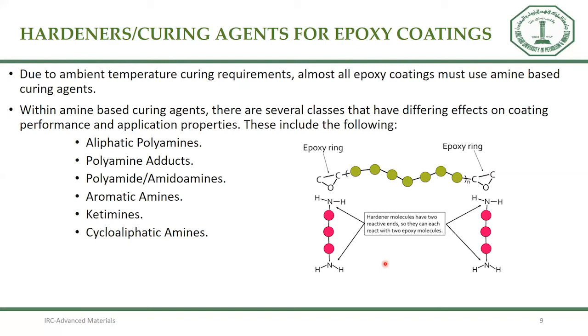But when you look at the commercial applications, in many cases we use amine-based hardeners because they can easily work in room temperature conditions. When you consider the amine-based ones, we have different categories like aliphatic amine, aromatic amine, cycloaliphatic amine, etc. Here, when you look at the amine structure, it has two amino groups at the two ends, so both ends can react with the epoxy resin and start the curing reactions.